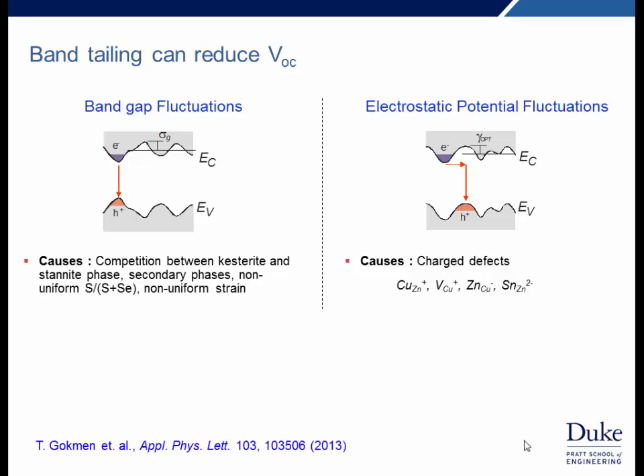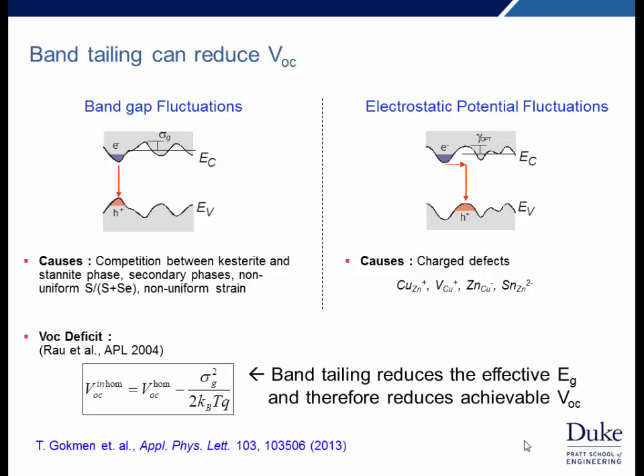What about bulk material? One of the things we were worried about was band tailing. Band tailing in the material, or states in the band gap, can arise from a number of different factors. One is band gap fluctuations, and this can come from non-uniform composition. And so this, for example, could arise from what I was talking about with the issue with particle aggregation. But also electrostatic potential fluctuations can also be an issue, and this arises from charge defects. In either case, band tailing reduces the effective band gap and therefore reduces the achievable open circuit voltage.